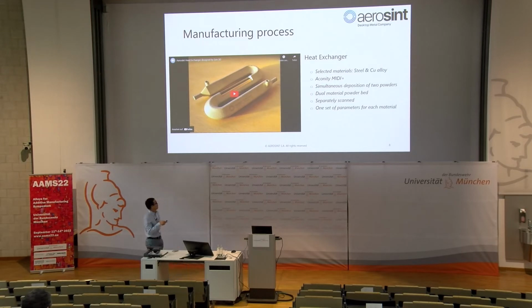In this case, we have the steel and the copper. This is very interesting to the industry because of the thermal conductivity of the copper and the mechanical strength provided by the steel. With our recoater, we can deposit the two materials on the layer. Since these two materials require different processing parameters, we have to lase them separately. In this case, we always lase the steel, followed by lasing the copper.